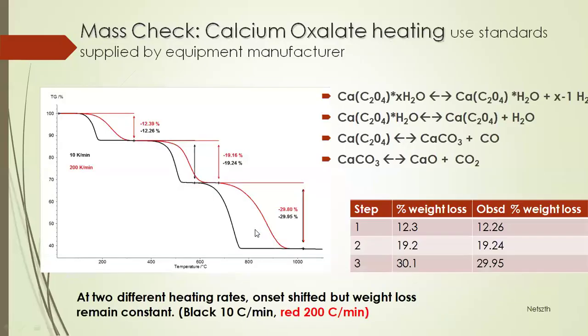And for weight calibration, always use dry calcium oxalate. Please remember, I'm using the word dry. Calcium oxalate absorbs water, so you have to dry the calcium oxalate. And why calcium oxalate? Because the reactions for calcium oxalate up to 800 degrees are known, and the weight losses or the residue that is to remain is known. So take calcium oxalate, dry it, and run it at 10 degrees centigrade. The black curve is the 10 degrees centigrade per minute curve.